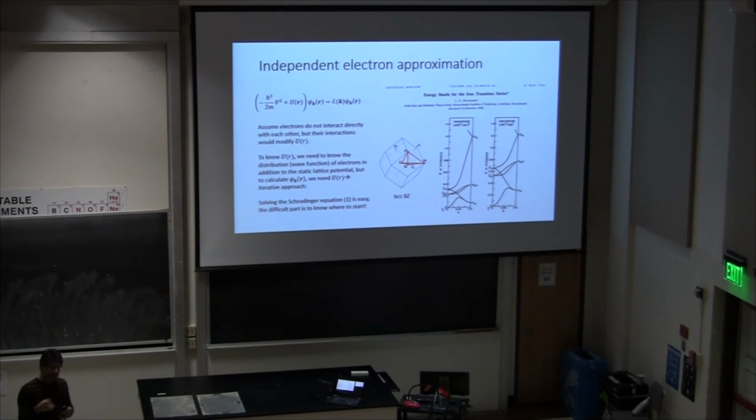Or, for example, based on the density of states. So here you can again look at the density of states. For example, you see this band here is flatter, right? And let's say your Fermi surface goes through here, okay? So this band is flatter. That means that it will give you a very large density of states. Then you measure, say, specific heat. And if you see a large specific heat corresponding to a large density of states, you would know that this one is better than that one. So even without ARPES, you can still tell which one is correct, which one is not correct. Yes. Next, you were saying something?